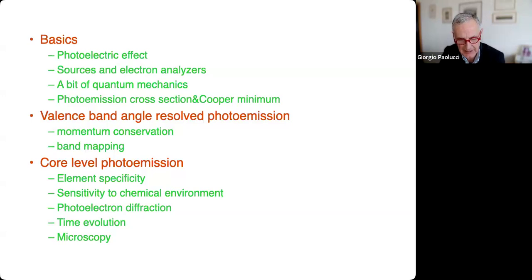Now, since we look at core levels, when you form a molecule, core levels are little affected. You get the shift which I mentioned, but the behavior as a function of energy does not change. A completely different story is, of course, for valence levels. For valence levels, they change completely, and that has to be done case by case, but it can be done. Not by me. I was trained to use screwdrivers, not pens and computers, but it can be calculated.